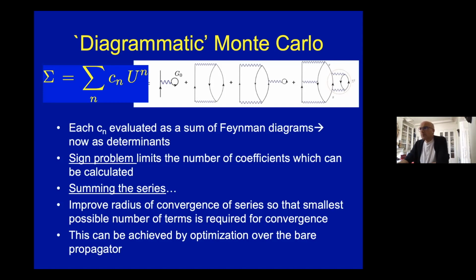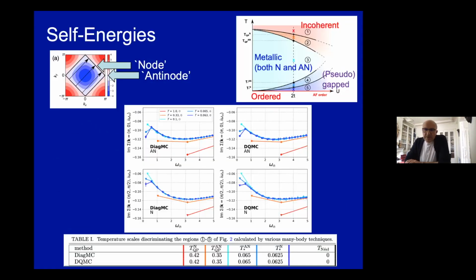Nonetheless, this can be successfully implemented in this specific case, and this slide demonstrates that you see these different regimes. Each of these curves here is a different temperature for the imaginary part of the self-energies for nodes and antinodes. Each of the colors corresponds to one of these five crossover regions, and these two columns show you that the diagrammatic Monte Carlo and determinantal Monte Carlo methods agree very accurately.